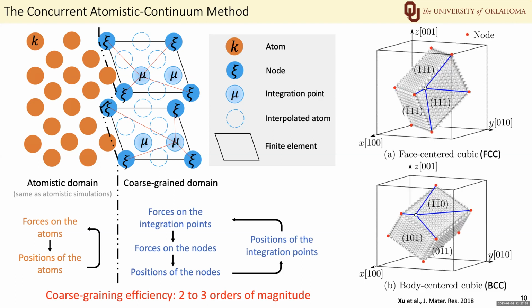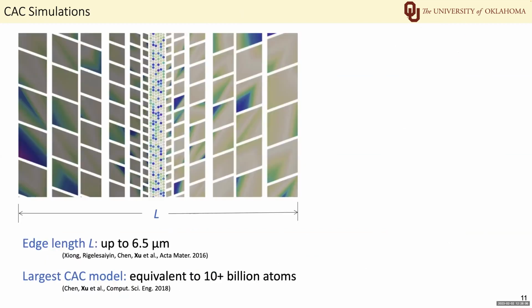Because we want to allow for dislocations in the coarse-grained domain, we use a 3D rhombohedral finite element with all the surfaces on the slip plane of the lattice. So in FCC lattices, the element surfaces are on one {111} plane, but in BCC lattices, they are on one {110} plane. The edge length of the CAC simulation cell can be up to 6.5 micrometers. The largest CAC model so far is equivalent to more than 10 billion atoms.